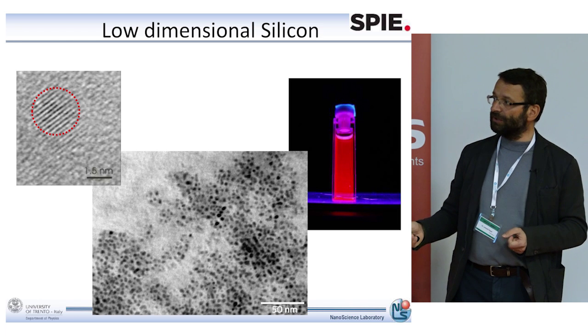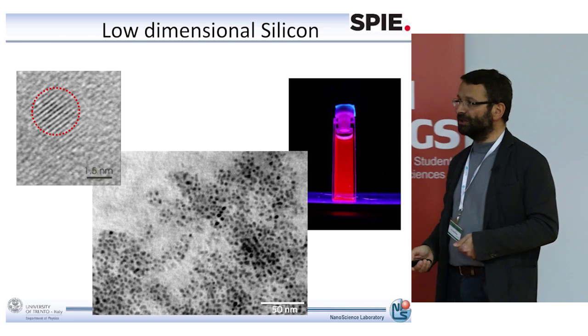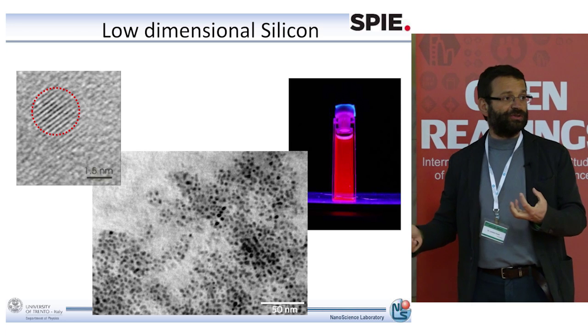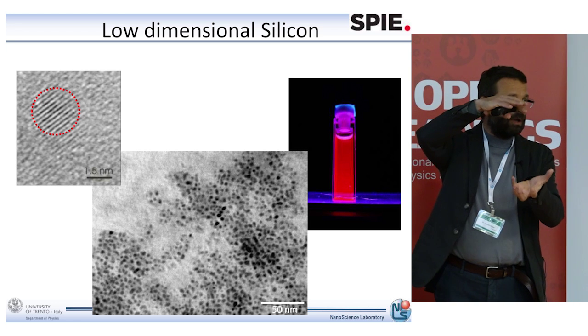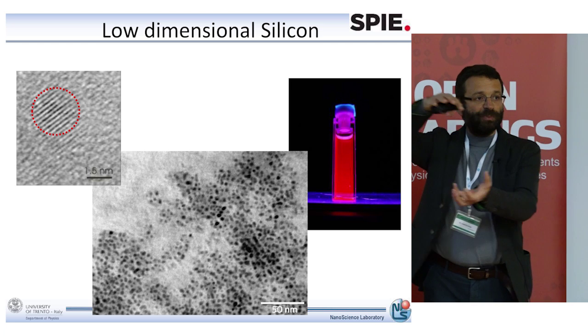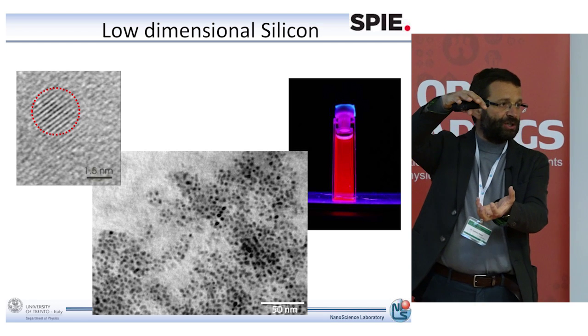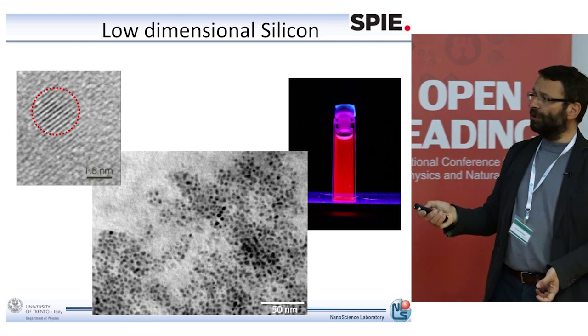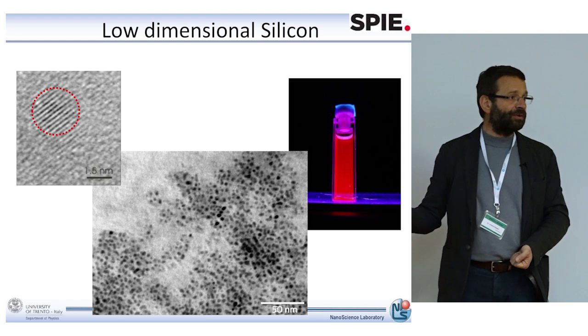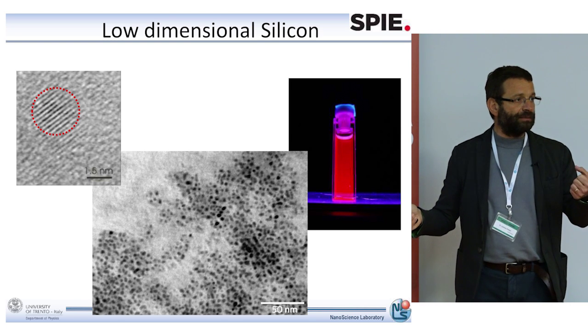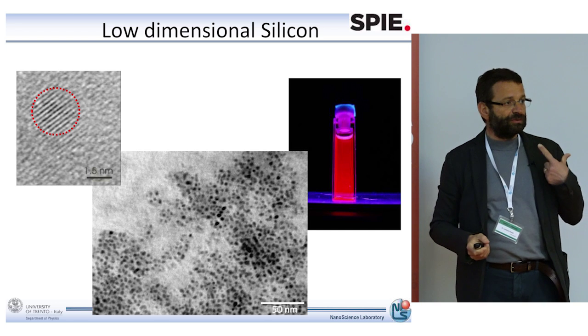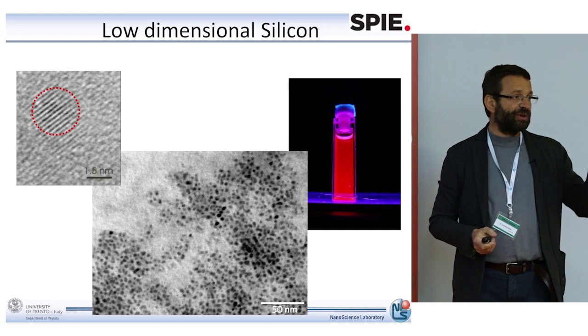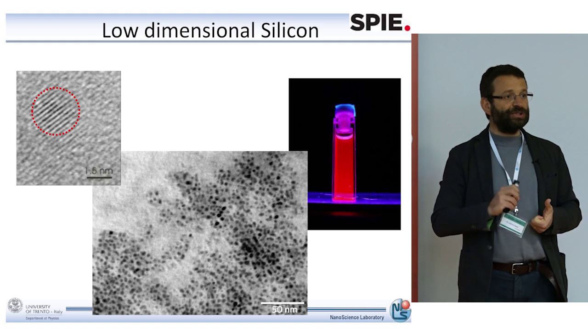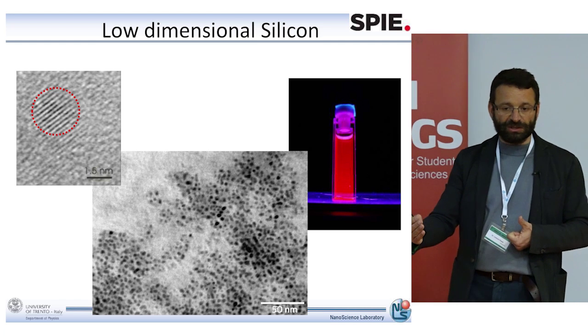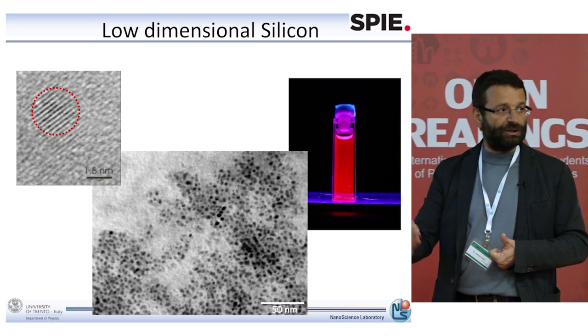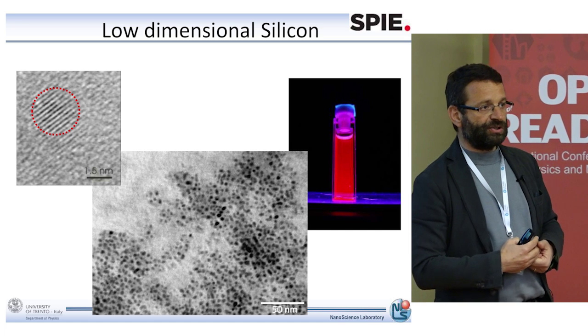So it's very easy. And what you immediately notice is that if you take those nanocrystals, disperse them in a colloidal suspension, and then expose this colloidal suspension to blue light, what you see is that this suspension glows in the red. So here you see two facts. The first one is that it's glowing. So by reducing the size of the nanocrystal, it is possible to get a quite efficient emission of light from silicon.